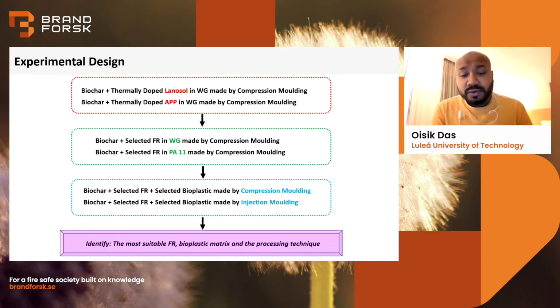Depending on that, we have used polyamide 11. Initially, we planned to use polylactic acid, but it was not available. But polyamide 11 was used, which is also a bioplastic made from castor oil. And then finally, we have tried to understand, once we have identified the better fire retardant and the better bioplastic, which processing method is more optimal, either compression molding or injection molding. And finally, to identify the most suitable fire retardant, most suitable bioplastic, and the most suitable processing technique.